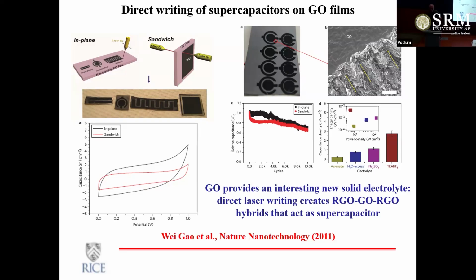So you have a contiguous film, but regions that were reduced were conducting, because when graphite gets oxidized and you make graphite oxide, it becomes less conducting and more insulating. So those regions of GO were used as electrolytes, and the regions that were reduced were used as electrodes. So you could actually build an entire device by simply laser patterning this graphene oxide film. It was a supercapacitor, and by adding some electrolytes into the graphene oxide, you could use it as an efficient separator plus electrolyte. So you can get a very thin film supercapacitor device by simply taking a GO film and locally patterning it.